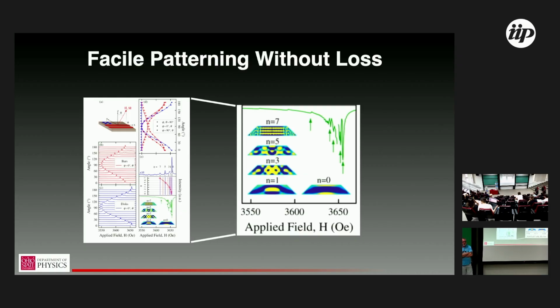And so I pushed him on this, and I was like, well, how do other people measure whether the surface is pinned? Let's just measure it. And it turns out they don't. Basically, they fit the model, and they do two fits, one for pinned versus unpinned, and the one that's a better fit to the data, they say, now we know that our surface is pinned. There are some pretty heroic measurements that one can do to measure just the surface pinning, but that's not at all straightforward. What would physically cause the pinning or a free boundary?